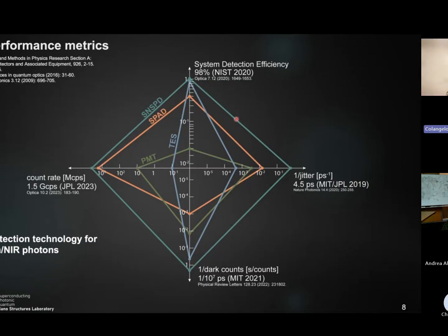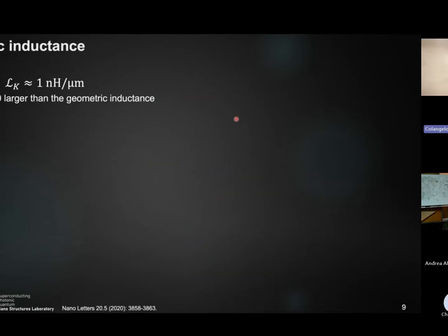So how do we actually solve these intrinsic trade-offs? That was my initial research. And we can see that this problem is actually given by some issues with the superconductor being a superconductor. So we do have the kinetic inductance, which is an inductive contribution of the superconductor given by the inertia of the Cooper pairs, and it's about 1 nanohenry per micron. Now, this number maybe doesn't say anything, but it's actually 1,000 times larger than the standard geometric inductance in this structure.